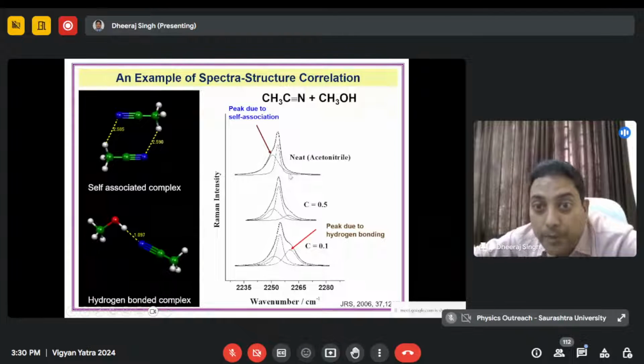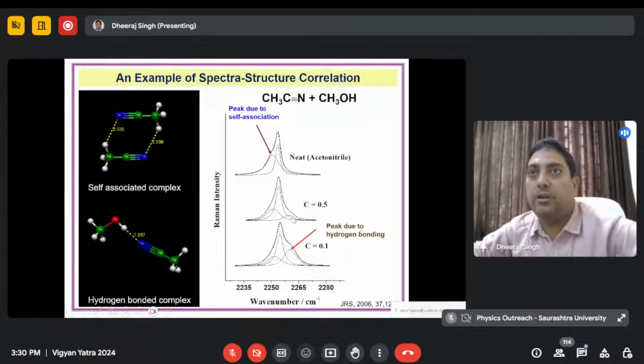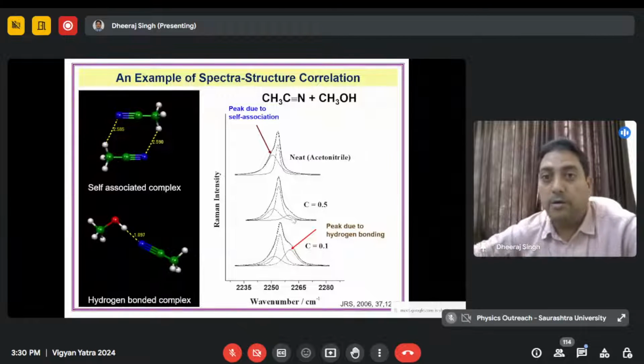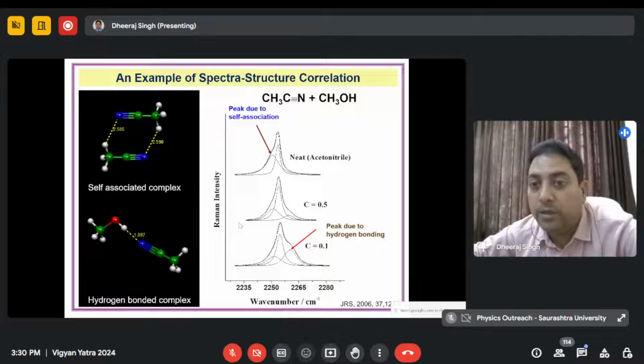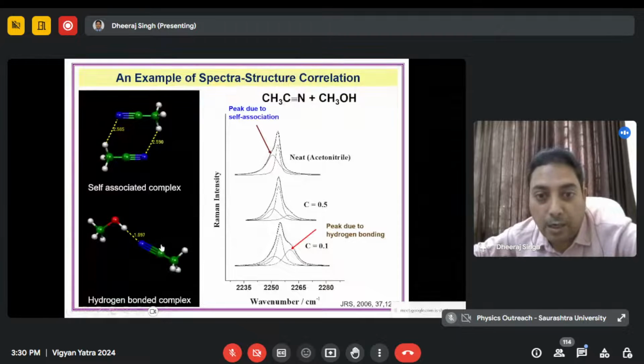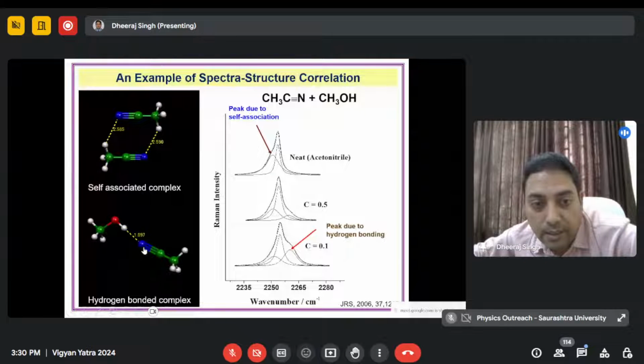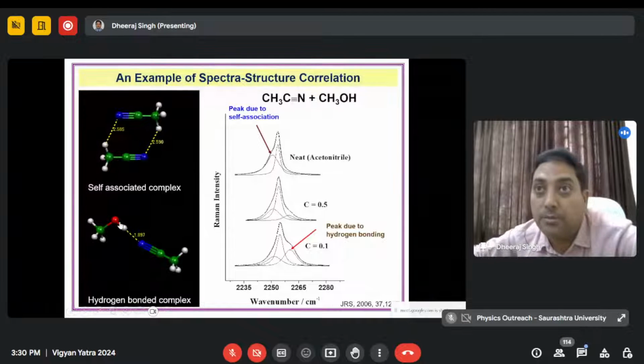And now a new peak is generated on the higher wave number side. You can see on the right-hand side that this peak was not obtained in the pure acetonitrile, but on the higher side a peak is generated. We call it the hydrogen bonded structure of acetonitrile with methanol. If we use DFT calculation theory, then we can see that this C triple bond is showing the dotted structure with HO. Means this C triple bond frequency is now affected by the vibrations of the methanol.